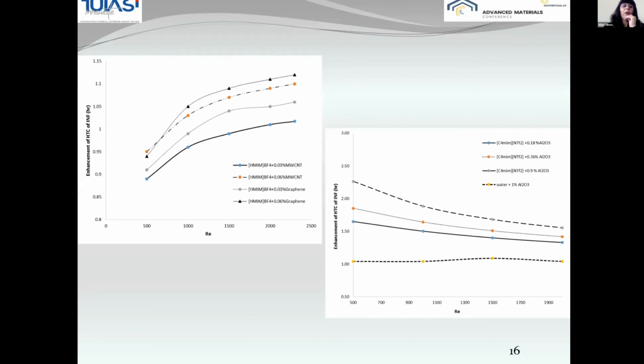Here are some of our experiments just to help you get an idea of the enhancement of heat transfer coefficient when you are talking about different ionic liquids with different kinds of nanoparticles. So here we have the addition of graphene and multi-wall carbon nanotubes, at very low percentages. And here we added alumina. And there is also a comparison with the basic nanofluid, that is water plus alumina.